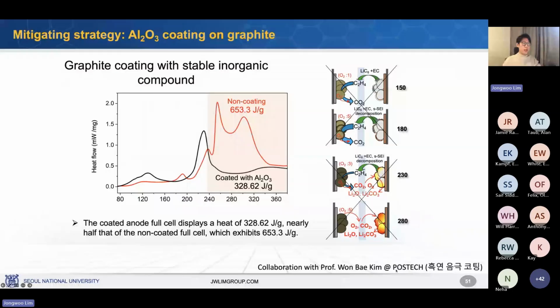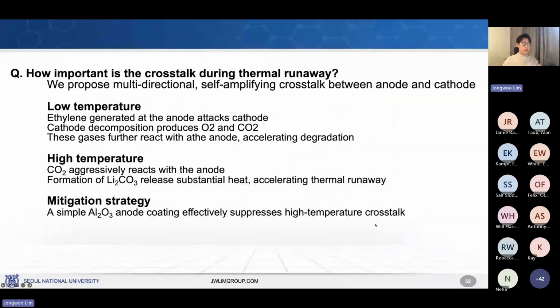So, answer to the question, how important is the crosstalk? They're very important. Multi-directional self-amplifying crosstalk is there. At the low temperature, ethylene gas produced from the anode attacks the cathode, produces CO2, and then also they attack the anode. At the very high temperature, we got a lot of CO2 from the cathode, and they attack the lithium inside the anode. In order to mitigate it, we simply overcoat the anode with the artificial SEI, which is, for example, aluminum oxide, so that we can suppress high temperature thermal runaway very effectively.